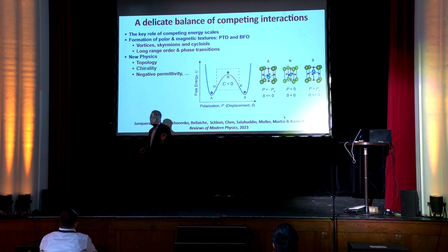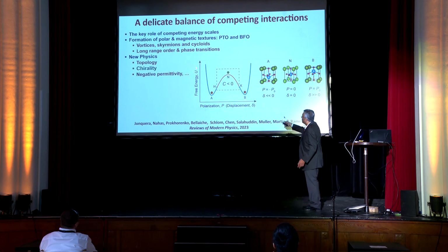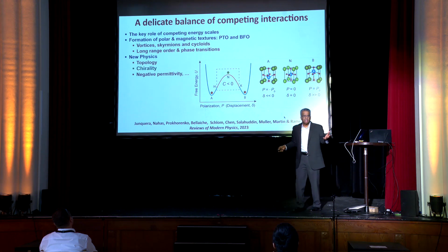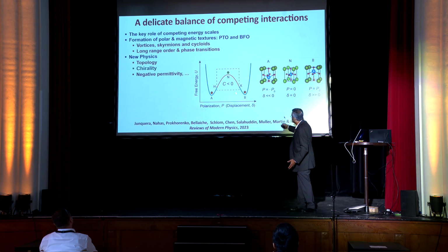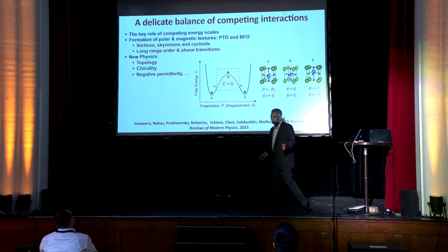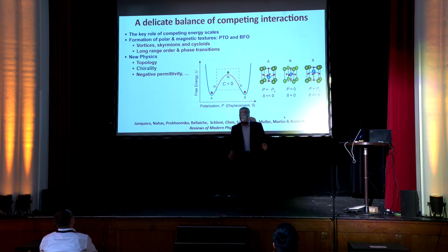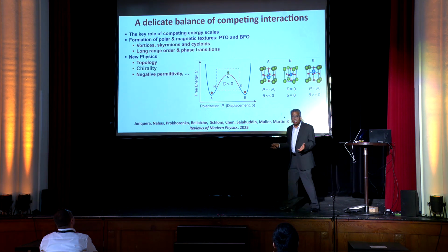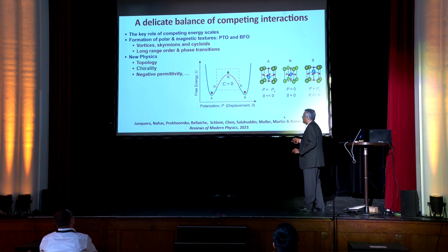Going away from metallic systems, we're now going to spend a few minutes on insulating systems. This is the case of a ferroelectric material, a very canonical system, lead titanate. Okay? So if you look at the classical thermodynamics of the system, it has a double well structure, which is shown here. And it's always been thought that this position, the end point, is not stable. And that's true. That's absolutely true. But if you now create a structure which has very different behavior, then that may not be true. This is what I'm going to take you through in the next few minutes.